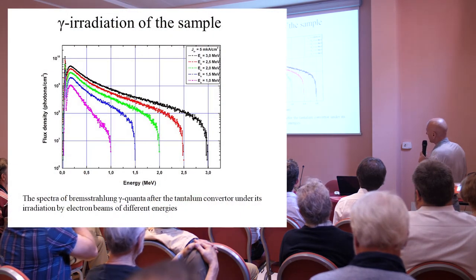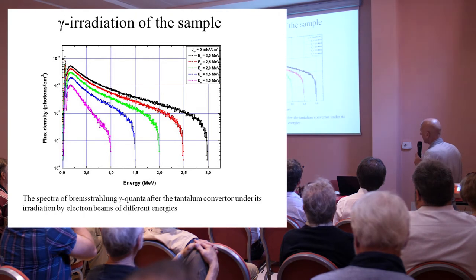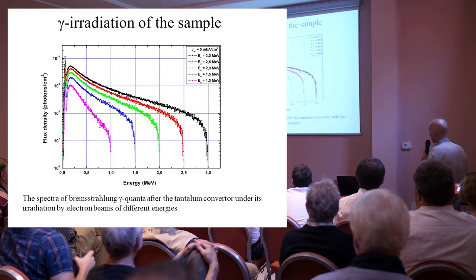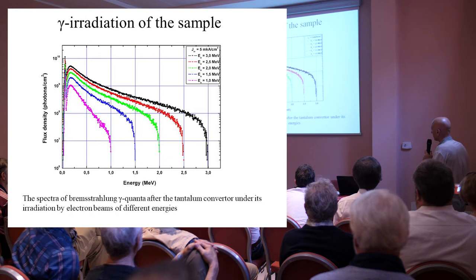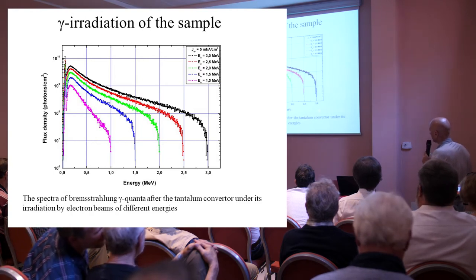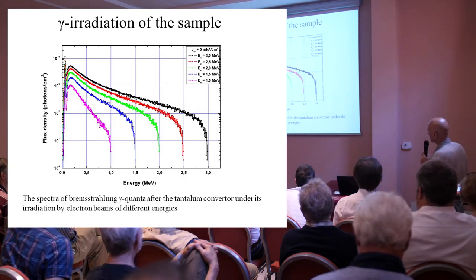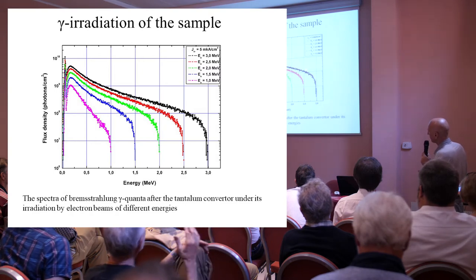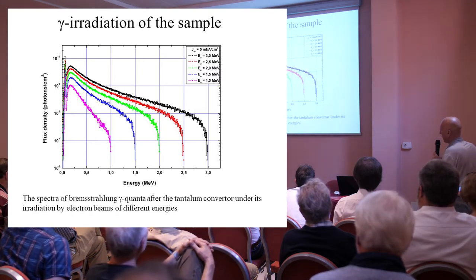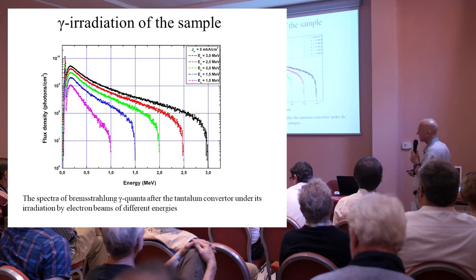Here is the scheme showing the Bremsstrahlung gamma quanta produced at the tantalum converter. For instance, if you're using 3 MeV, you produce this kind of spectra. If you use 1 MeV, this kind of spectrum. And the idea is that if you irradiate